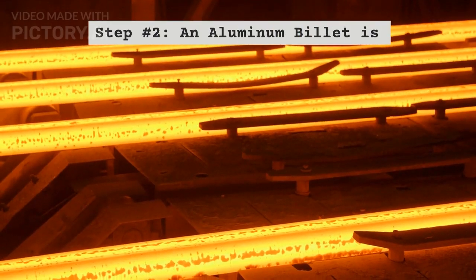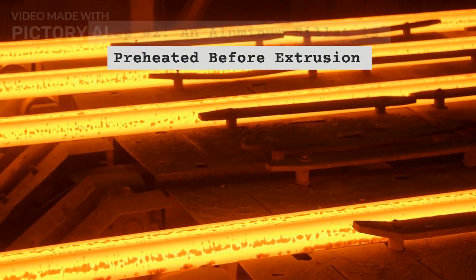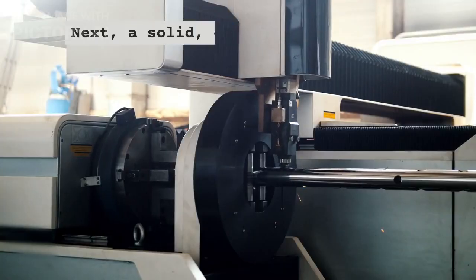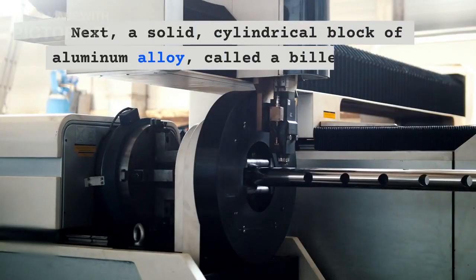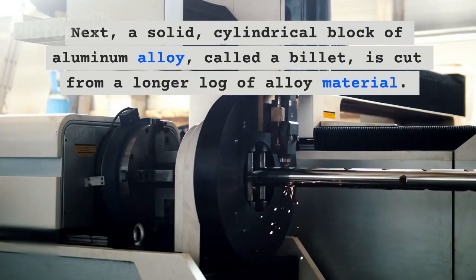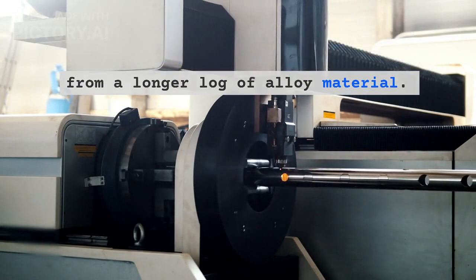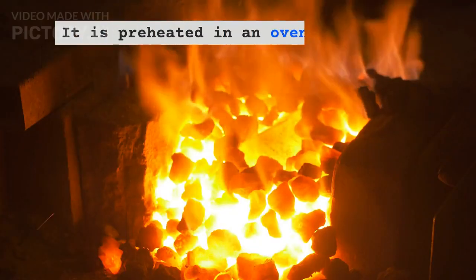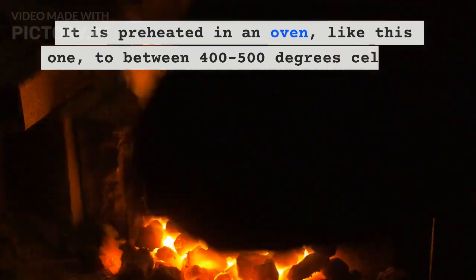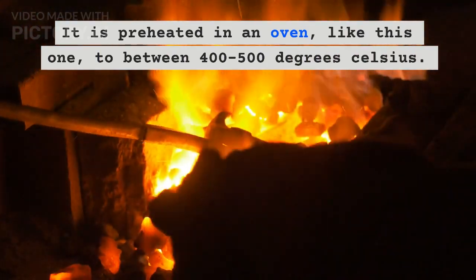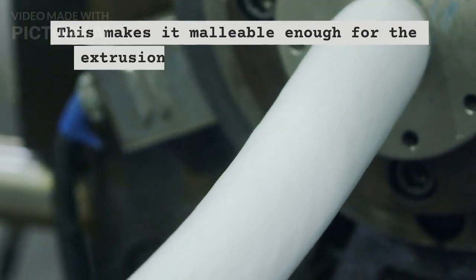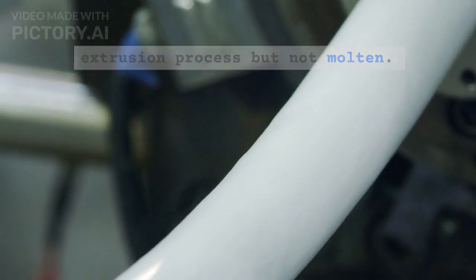Step 2. An aluminum billet is preheated before extrusion. Next, a solid cylindrical block of aluminum alloy, called a billet, is cut from a longer log of alloy material. It is preheated in an oven, like this one, to between 400 to 500 degrees Celsius. This makes it malleable enough for the extrusion process, but not molten.